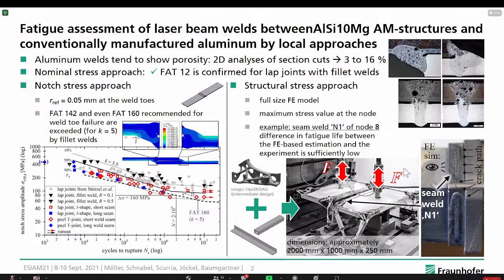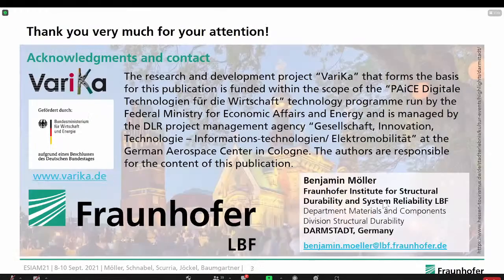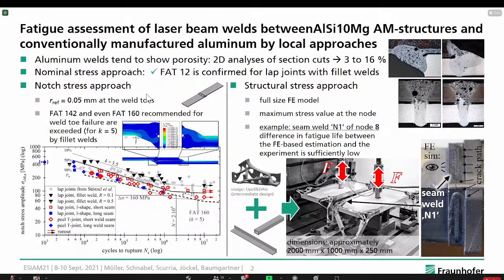And in these experimental investigations, we could see that we also find cracks in at least 3 out of 7 experiments, which are running through the laser beam welded seams, and therefore cause failure of these more or less complex structures. From the numerical point of view, we see that the notch stress approach is not applicable due to these full size models, so a structural stress approach has to be chosen, which was in good agreement in this case for the whole battery carrier to estimate the fatigue life of such a weld seam. This is more or less the outcome of the work, and I think there is still some work to do. So thank you, and I'm open for questions.